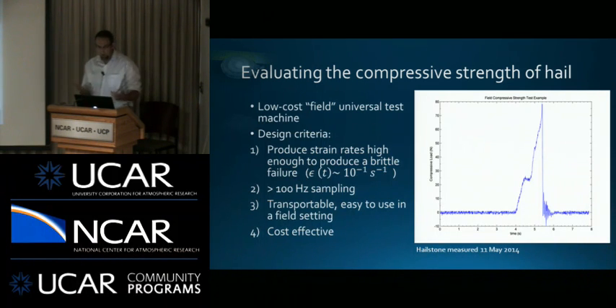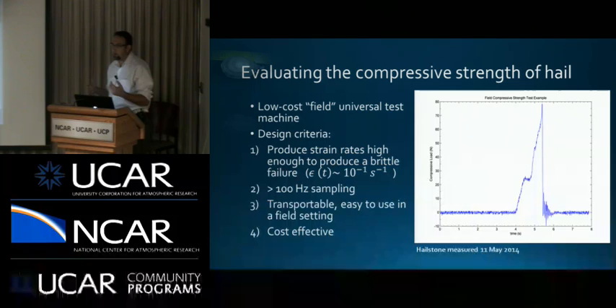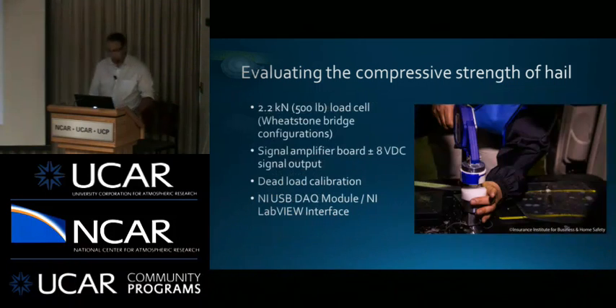Now, I will say there are some drawbacks to this simple system. Whereas with a universal test apparatus you can apply a constant strain rate, this is manual operation, so you don't get a very clean displacement rate. But we did some comparisons with a universal test machine and it came out fairly reasonable. I'll get to that in a second. So what we chose to use was a 500-pound, or 2.2 kilonewton, load cell.